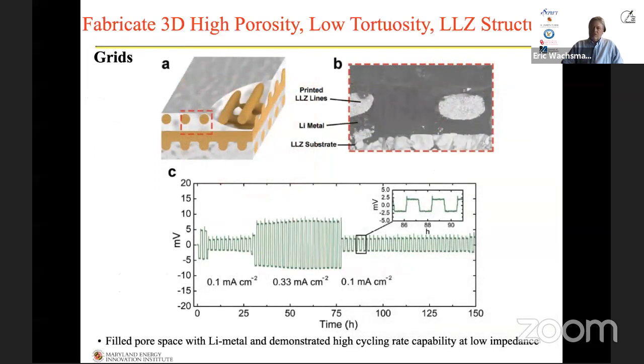In terms of lithium cycling, as an example of the electrochemical characterization we've done, again, we can melt lithium. It fills the pores of the ceramic. You can see conceptually on the left with A, an actual SEM image on the right with B. And then the data below, C, is the cycling data. So we're basically cycling lithium back and forth at room temperature between the two sides of this structure, achieving 0.1 milliamps per square centimeter, 0.33 milliamps per square centimeter, et cetera.